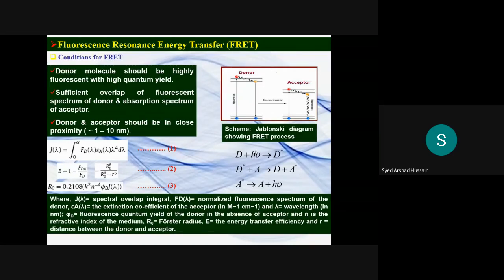So one can have an idea about the molecular organizations by studying FRET also. So this is one issue. And there are other criteria for FRET to occur. These are, for example, the donor molecule should be very highly fluorescent, with a very high quantum yield. There should be sufficient overlap between the fluorescence spectrum of the donor and the absorption spectrum of the acceptor. And spectral orientation is also a very important factor. So I am not going into details of that.